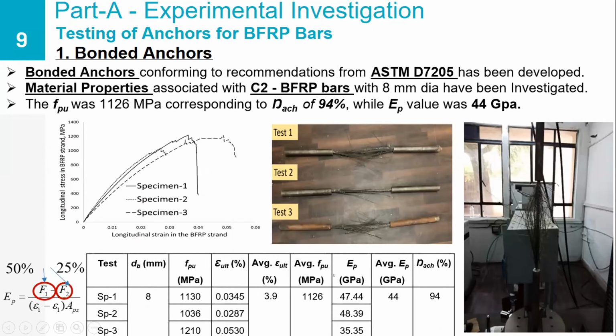And these are the stress strain curves that have been obtained. So the average strength that we got from these bars was around 1100 MPa. And the modulus of elasticity that we obtained by interpolating the stresses and strains between 50% and 25% of the ultimate strength was obtained as 44 GPa. And we can see that the fabricator claimed a tensile strength of 1200 MPa for these bars.